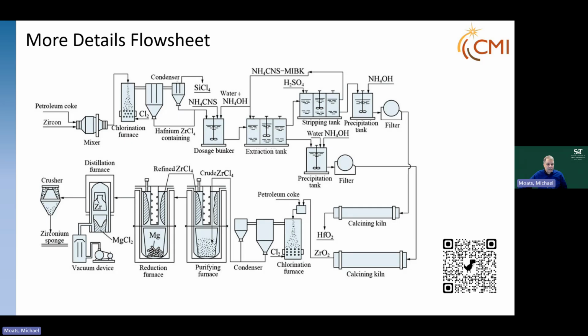And then we're going to take that zirconium tetrachloride and hafnium tetrachloride and go through solvent extraction. We're going to separate them. The hafnium is going to come out, and we're going to go through a calcining furnace to make hafnium oxide. The zirconium comes out. We precipitate it and go through a calcining kiln to make zirconia. We are going to go through a carbochlorination furnace to put it back to zirconium tetrachloride, and we're going to go into the Kroll process, where zirconium is reduced by magnesium and then distilled, and we eventually get this zirconium sponge. And I'm not going to go any farther than that in the discussion. I'm just going to stop at zirconium sponge, because the rest is, we'll say, more physical metallurgy than extractive metallurgy.